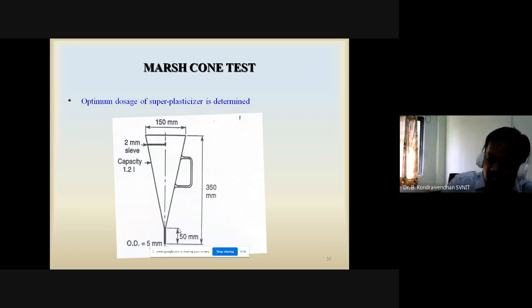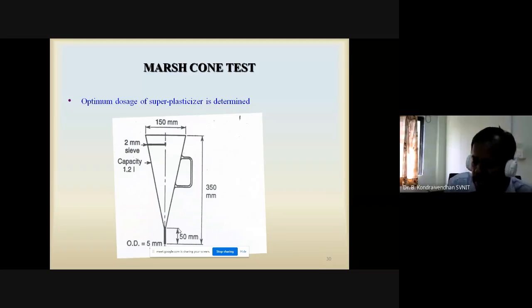At one stage, even though you are increasing the dosage, there will be no reduction in time. That means there is an optimum dosage. Once you reach it, you have to stop. That is your optimum dosage. That's how you have to determine the optimum dosage of the superplasticizer.